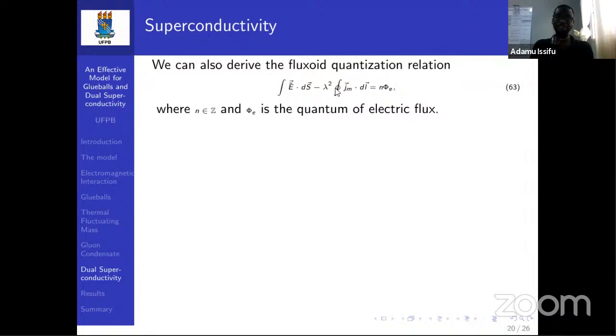And this, we can express the fluxoid quantization relation. This is typical for type 2 superconductors, where you exceed the lower field, that it has a lower and upper field. So when you exceed the lower field, you have some vortices penetrating the superconductor, and this is the quanta of those vortices that enter the superconductor. So N is an integer, and then this is the quantum of the electric flux.